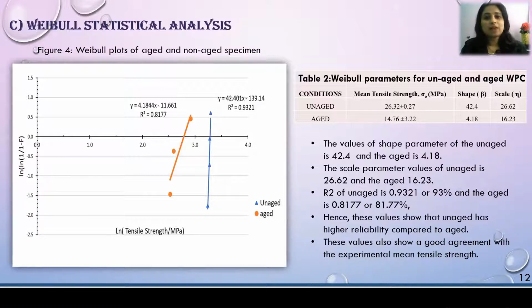Besides that, the R-square value from the graph of unaged is higher at 93% compared to the aged, which is 81.77%. Hence, these values show a good agreement with the experimental mean tensile strength value. Therefore, it can be said that the unaged shows higher reliability compared to the aged.